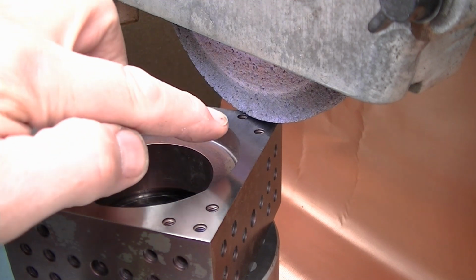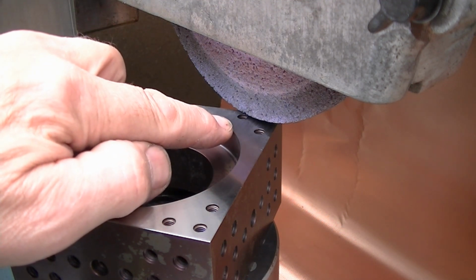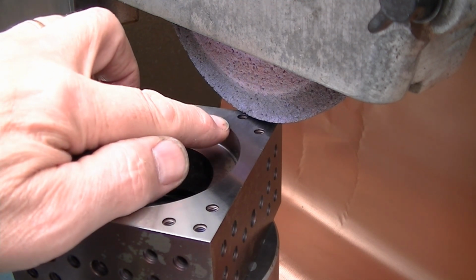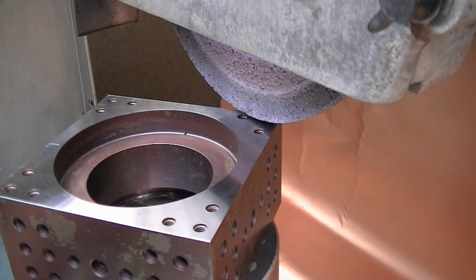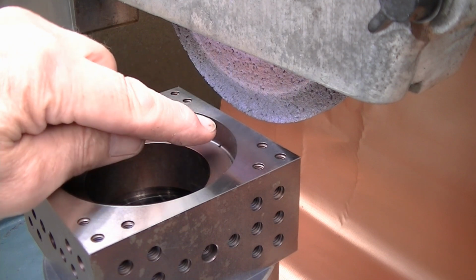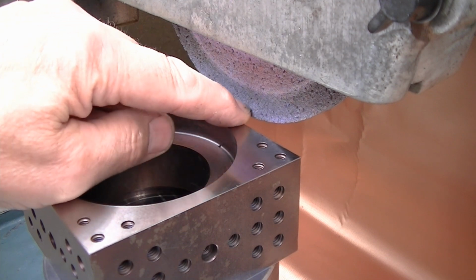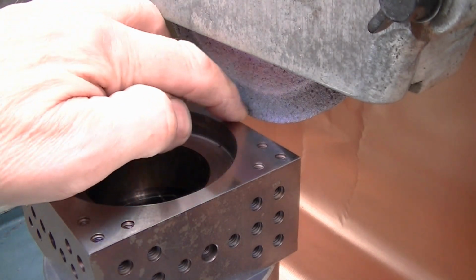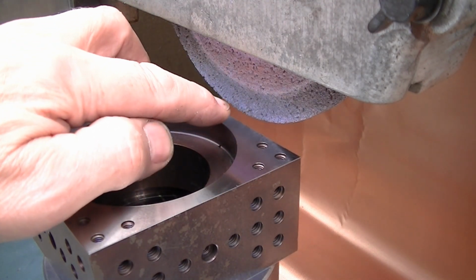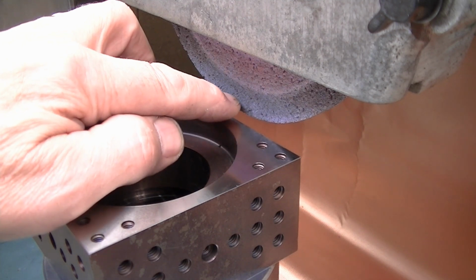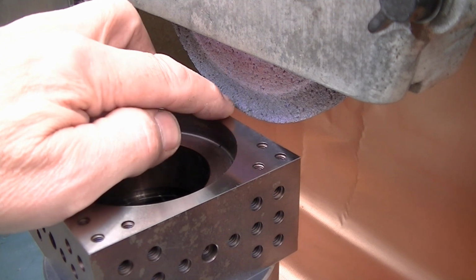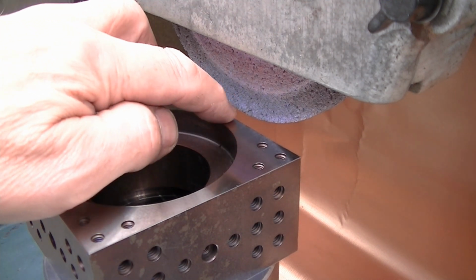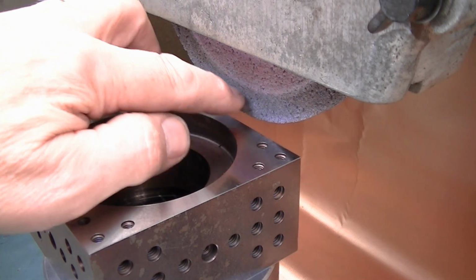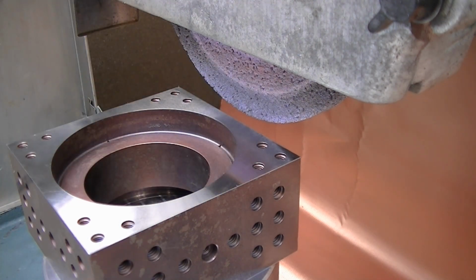Also, if this was just a cylindrical spacer, you have the situation, and people who have ground much are probably familiar with this, where when you come off the part, the engagement with the wheel is changing. If we were moving over here and we're on this side, the edge of the wheel starts on, the full wheel width is engaged, and off, you can have a tendency to have a curved situation where the grinder grinds higher when the full wheel width is engaged, and then as the edge of the wheel tails off and the engaged width keeps decreasing, it's able to grind deeper and deeper because there's less and less wheel to support, and the wheel actually flexes down into the part deeper on each side of the cut, on each side of the part.